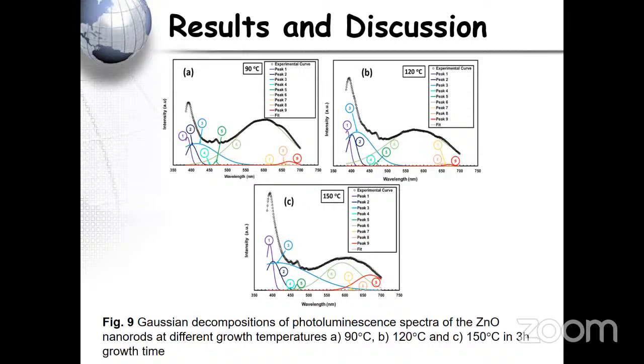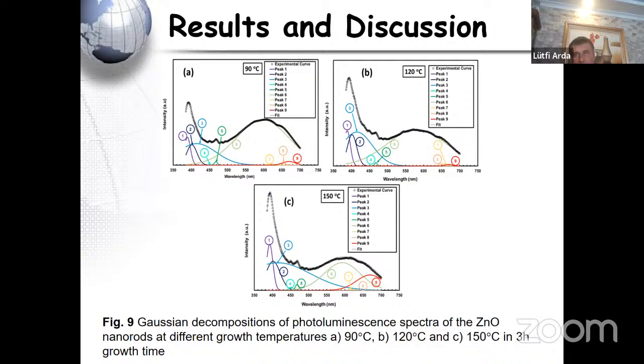The growth temperature plays a crucial role in reducing oxygen defects in zinc oxide nanorods. This outcome is also in excellent agreement with the XRD spectrum. Generally, crystal structure defects are detected repeatedly in one-dimensional zinc oxide nanostructures produced by hydrothermal synthesis using low growth temperature. Accordingly, we can conclude that the reactions in the hydrothermal method may produce double charged oxygen vacancies and oxygen interstitials, and thus affect the luminescence property of zinc oxide nanorods. Zinc oxide nanorods should be fabricated by choosing the appropriate time and temperature according to the need for donor and acceptor, depending on the usage place.